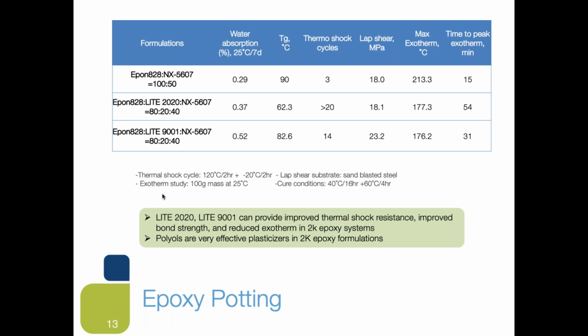When it comes to potting, we know that epoxy and polyurethanes are used. However, if you are dealing with the epoxy system, we have also experienced some limitations from epoxy. Epoxy tends to be quite brittle, which impacts the thermal shock resistance, and also tends to have a higher exotherm. So in this study, we used a polyol or monol like 2020 as a plasticizer to improve the thermal shock resistance and also lower the exotherm temperature. As you can see, when we use 20% of LITE 2020 and LITE 9001 in the typical epoxy system, what we have seen is